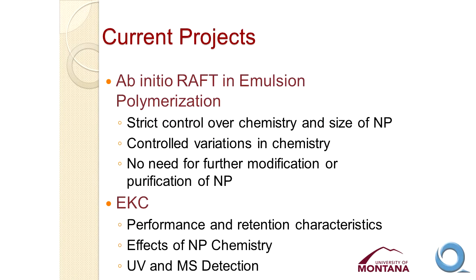All right, so currently what we're working on is the use of reversible addition fragmentation transfer polymerization, a controlled polymerization technique, so that we can control the size and structure of our polymers to generate nanoparticles that we can use as pseudostationary phases. And we're characterizing their applicability in electrokinetic chromatography, looking at performance, looking at effects of changes to the chemistry of the nanoparticles, and also confirming that we can use both UV and mass spec detection.